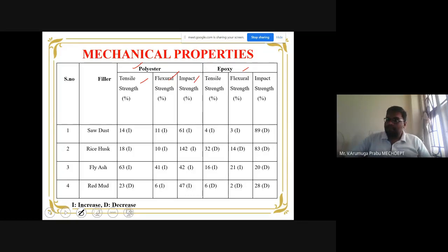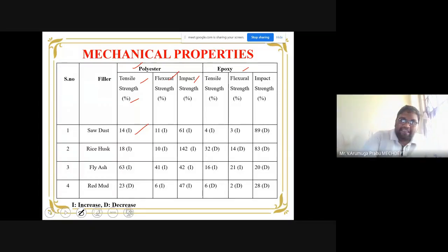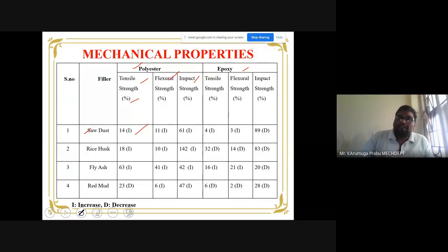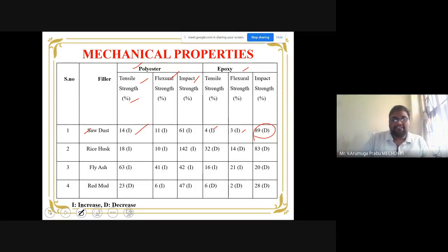So now here, the interesting results that we obtained are tabulated. Here the I indicates the increase, and all the values are in terms of percentage, the increase and the decrease in strength. Now, do you note, in the case of sawdust waste, both polyester and epoxy show a considerable increase in all the strengths except this one particular case. In all other cases, if you note, 14% increase, 11% increase, 61% increase. So in the case of polyester, all show the increasing trend.